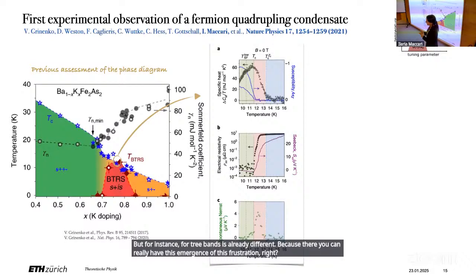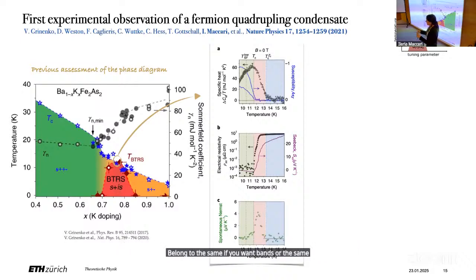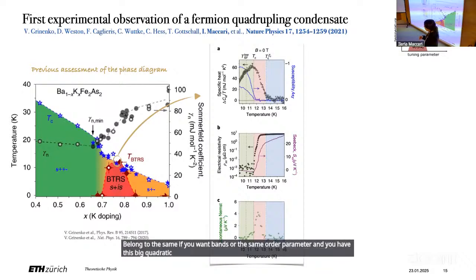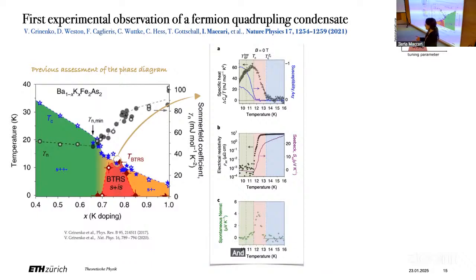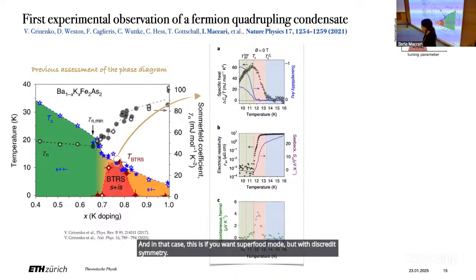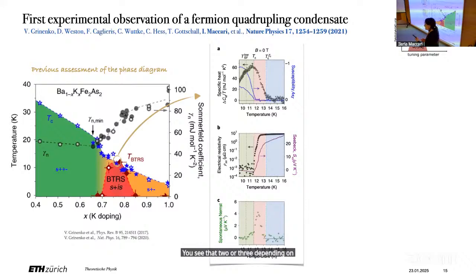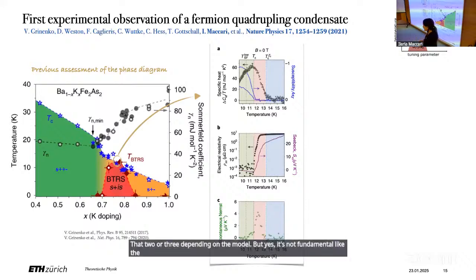Or in an unconventional superconducting state, like the one I studied for magic angle twisted bilayer graphene, where you don't have this Josephson coupling, because the two components belong to the same band, so the same order parameter, and you have this biquadratic Josephson term, which again locks the phase in these two possible chiralities. In that case it is a superfluid mode, but with a discrete symmetry, which is Z2 or Z3, depending on the model. But yes, it's not fundamental like the gauge symmetry. Thanks.